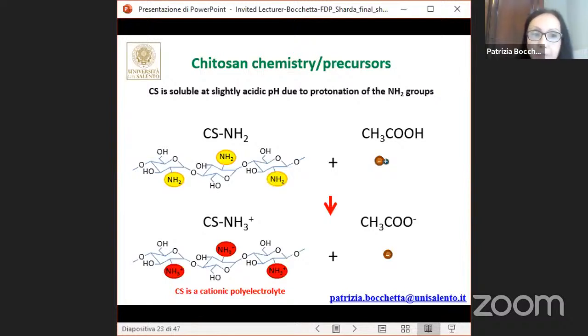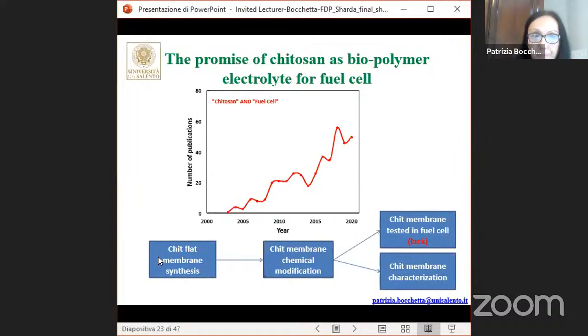So chitosan, as said before, is soluble in slightly acidic solution, so it is a cationic polyelectrolyte, thanks to the protonation of the amine groups and breaking of hydrogen bonds. Thanks to this chemistry, chitosan solutions are often used as a precursor to synthesize polymer membranes. The promise of chitosan as biopolymer electrolyte for fuel cells is reflected by the increase in research interest along the years.